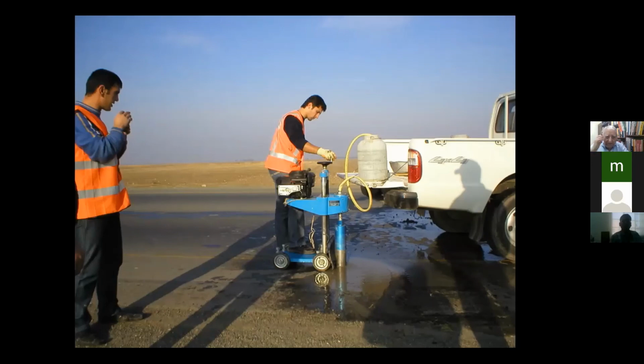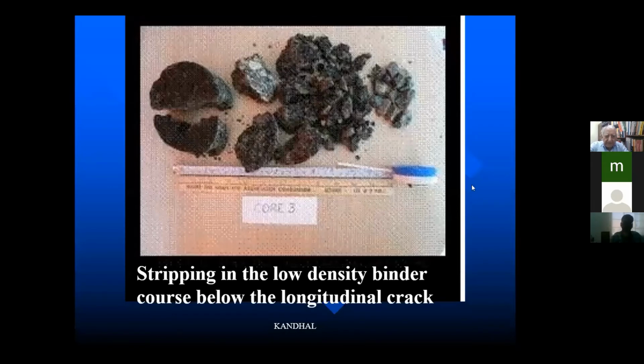What we found was that the surface course was okay, intact here. You can see this is the crack here, and the binder course was 50% stripped. What was happening is that the density of the binder course was very, very low. Below the crack, the density was very poor. Away from the crack, density was fine. In the DBM, the binder course, that we found out.